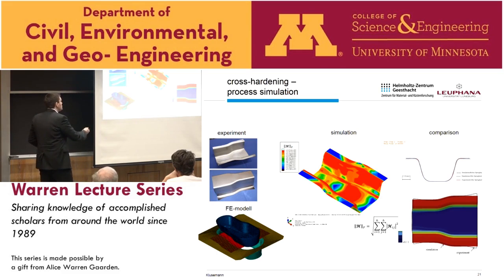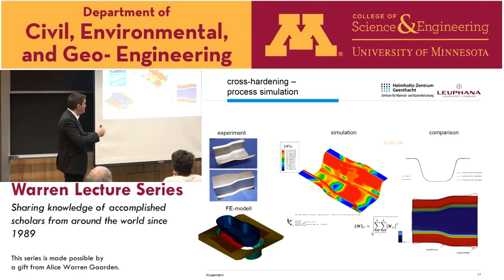And then we could, of course, see that there were some regions which have a stronger contribution than others. And this could be used, of course, as a first follow-up, to take, for example, specimens out of that and do some tensile tests to actually investigate the kind of hardening behavior which this material had at this position. But we could already predict that.